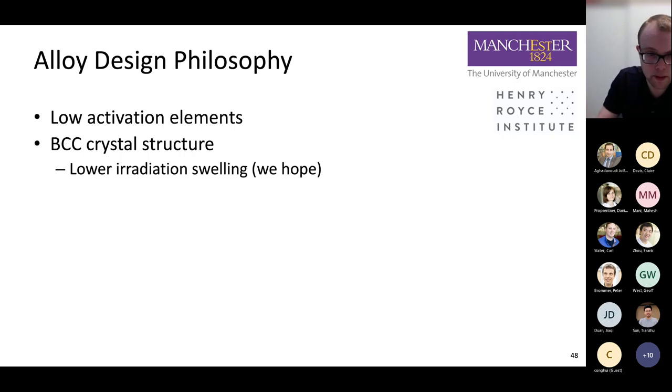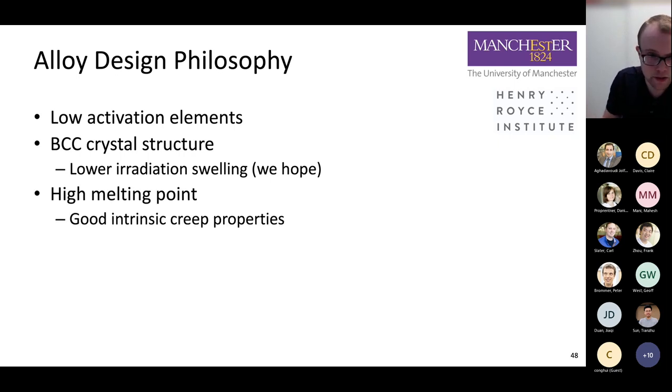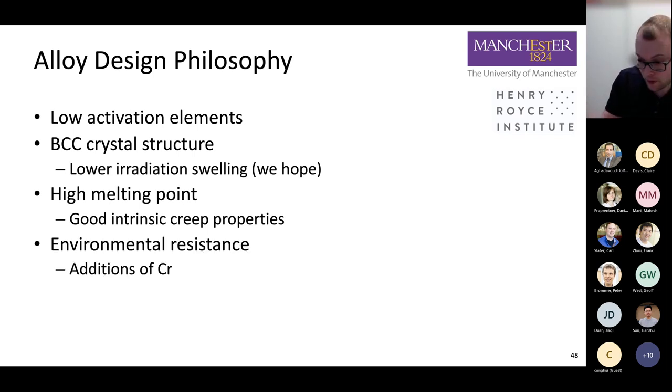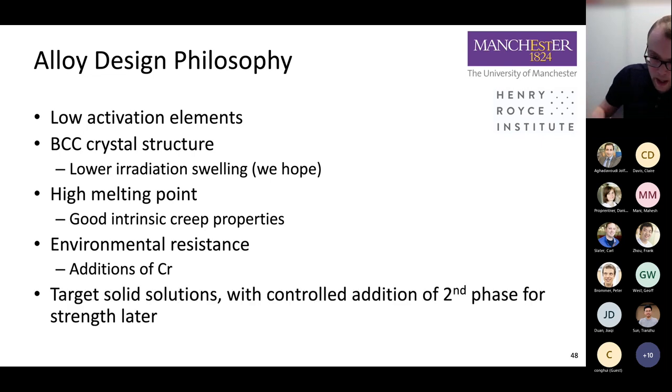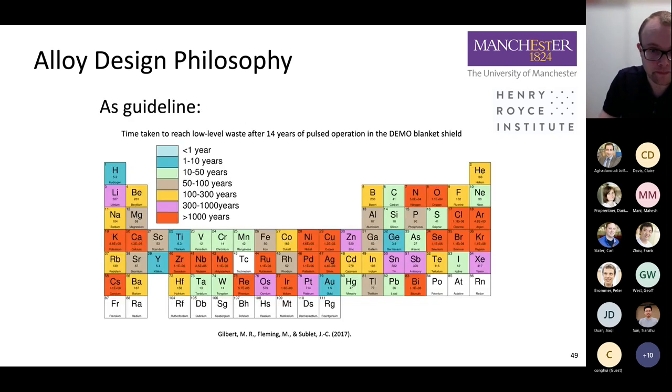Hopefully, this means that we get a lower irradiation swelling. We've looked at high melting point elements for good intrinsic creep properties, and we've also added elements like chromium for environmental resistance. We targeted solid solutions to begin with, so elements that we think are compatible with each other, in order to then introduce second phases for strength later on.